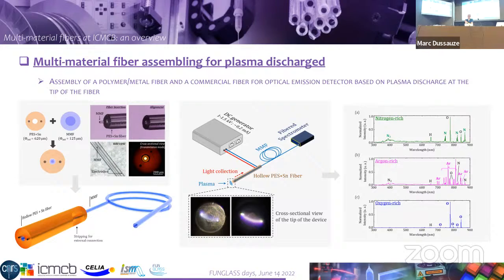We have some people currently working on this research axis to improve the process, to have a stabilized plasma, to lower the damaging of the tin electrodes at the exit, because this is something that can actually occur. Now the issue is solved, but at the time we had quite a strong damaging of the tin electrodes. Now it's not the case anymore. And again, as I said already, research that is now conducted is replacing these commercial fibers by homemade fibers that are, for instance, more transparent into the infrared if we want to observe other effects.